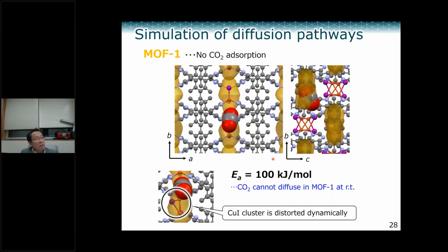Okay, this slide shows the result for MOF1, the 2D layer MOF. In this case, it is supposed to show no CO₂ absorption curve. This is a front view, this is a side view. Please pay attention here. This is actually the connected copper iodide dimer unit. As you can notice, this iodide is moving a lot. This is the initial position, then this is a saddle point, a transition point. Because of this large distortion, the activation energy is quite large, 100 kilojoule per mole. This value makes it almost impossible for CO₂ to move to another void. So Matlantis predicts, in this case, no CO₂ absorption curve, according to this activation energy.